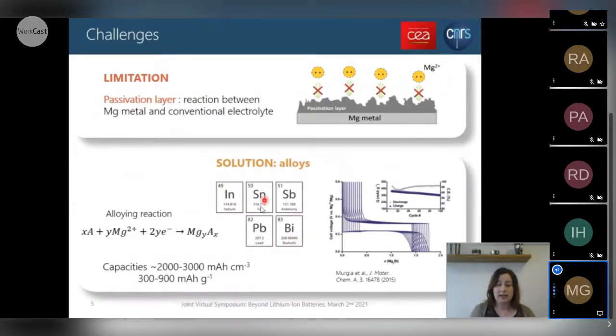These elements form alloys with magnesium following this reaction. They are, for example, indium, tin, antimony, lead, and bismuth, which have been mainly investigated first by Toyota and Bertolot's group. And they present capacities in the order of 2,000 to 3,000 milliamp hour per cubic centimeter and 300 to 900 milliamp hour per gram.